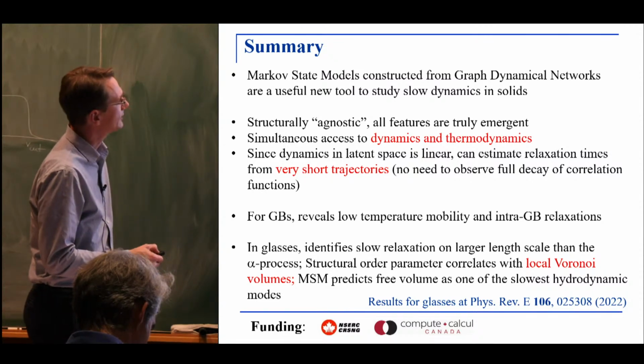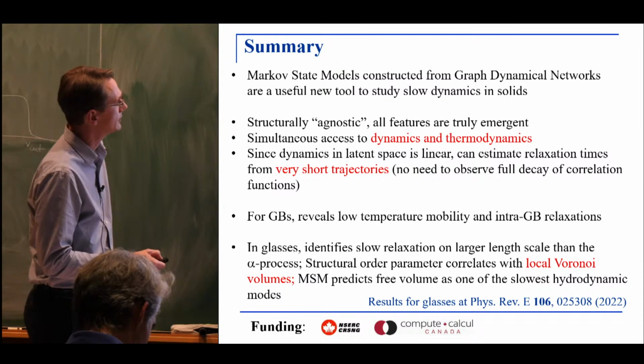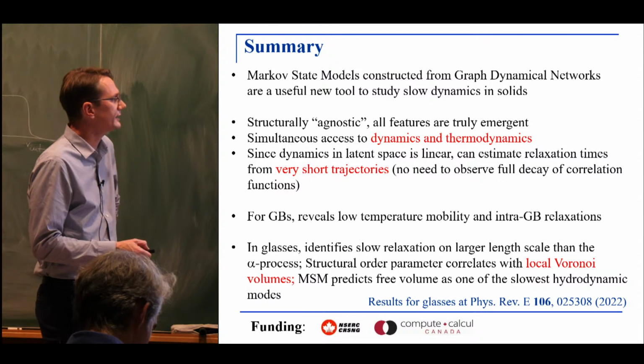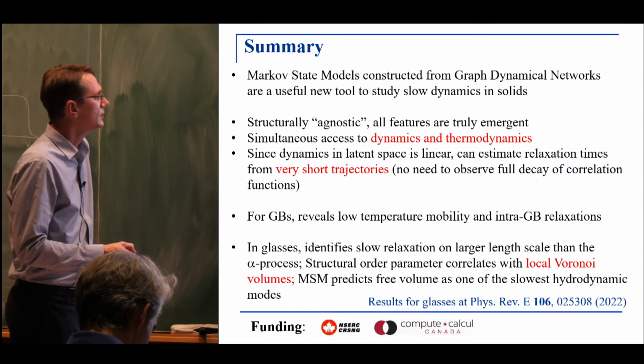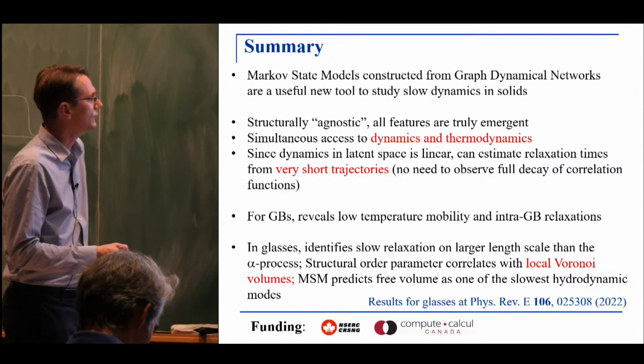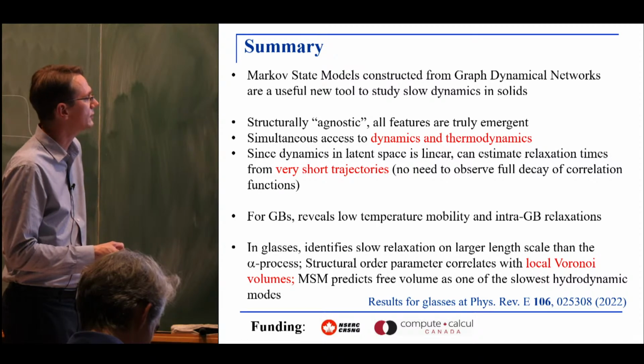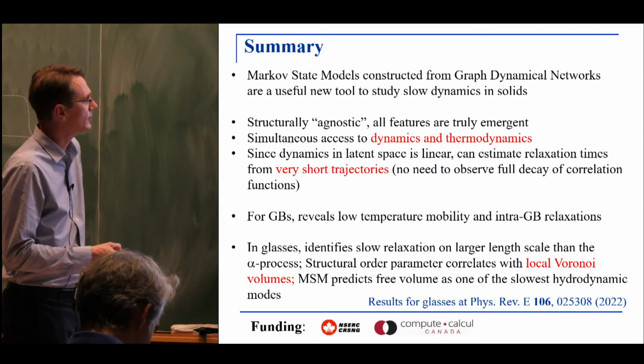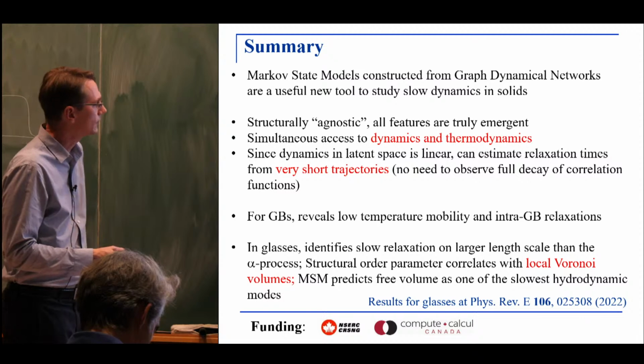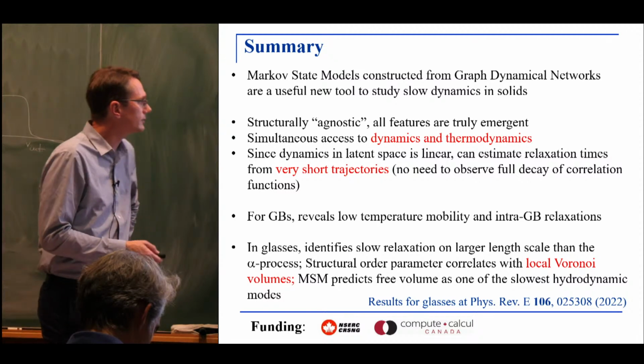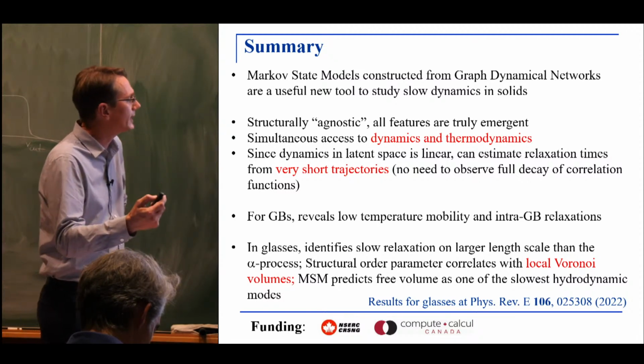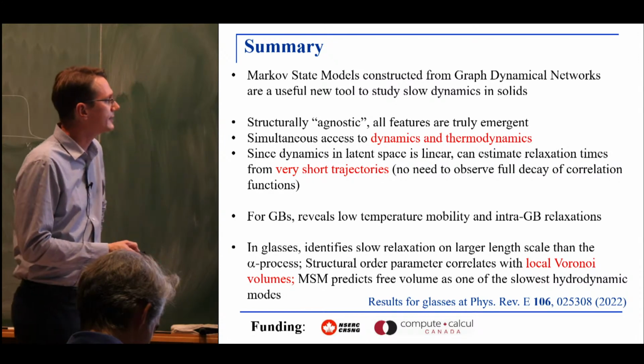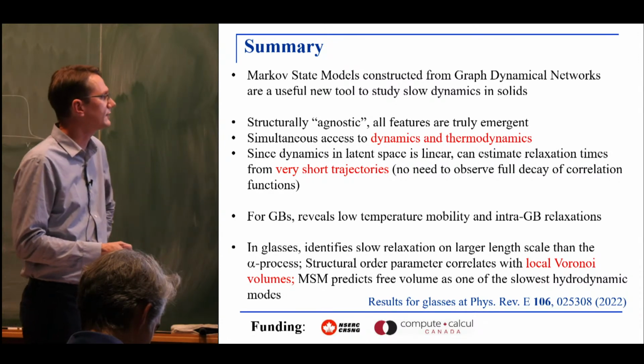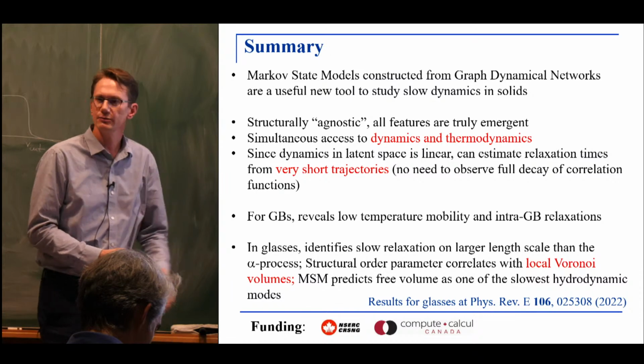In the grain boundary case, the timescales that emerge relate to the actual mobility of the interface. In glasses, we find a timescale that seems to correspond to the relaxation of local Voronoi volumes. That tends to be larger than the conventionally discussed alpha process. And as Daniele pointed out, the hydrodynamic variable that emerges here does seem to be related to free volume or local density fluctuations. So that's what I wanted to tell you.